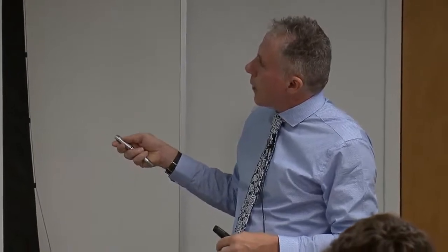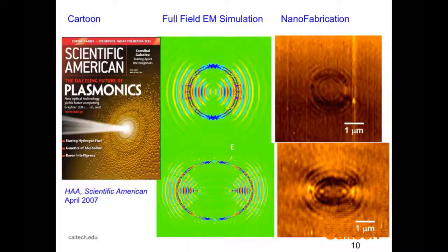And you can see here these beautiful sub-wavelength ripples, like the water waves after you drop a rock into a pond, propagating out and backwards. But these are nanoscale waves of bound surface plasmon modes that were created. Even though the surface waves are bound to the surface, you can't see them directly in the far field. By using the resist, we were able to image the fields in the near field.